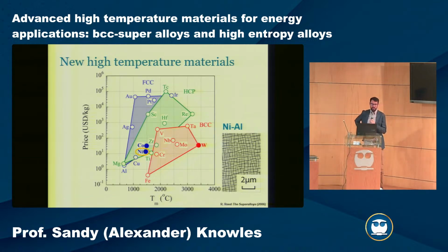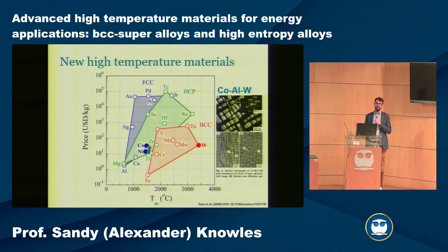So when we think about looking at alternative high temperature materials, we said earlier on that the nickel superalloys are hitting almost a physical limit. And part of that physical limit is probably based off the melting temperature. If something's molten, it's not going to be a very good structural material. So one first proxy we could use is to try to design and select different materials with higher melting points. So rather than nickel-based superalloys, we could go to cobalt-based superalloys, and there's quite a number of research groups that are doing this internationally. And you can get, again, a gamma prime microstructure where you get the high temperature strength, creep resistance, oxidation resistance. So with cobalt, you get maybe maximum 150 degrees, but it's also not that simple.